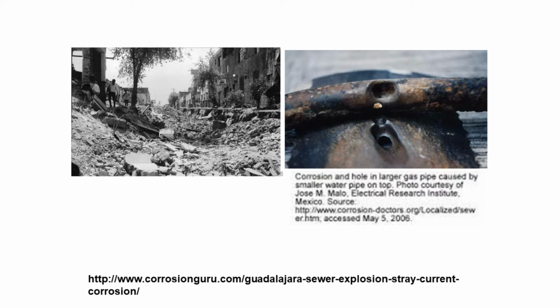However, this system suffered from stray current corrosion. The ICCP system caused an anode to form on the water pipeline immediately where they were closest, and the anode on the water pipeline overwhelmed the capacity of the galvanization to protect it. So after some time, the zinc in the area was worn out, and the water pipeline began to dissolve through, leaving this characteristic, very concentrated, large hole, which is often formed by stray current corrosion.